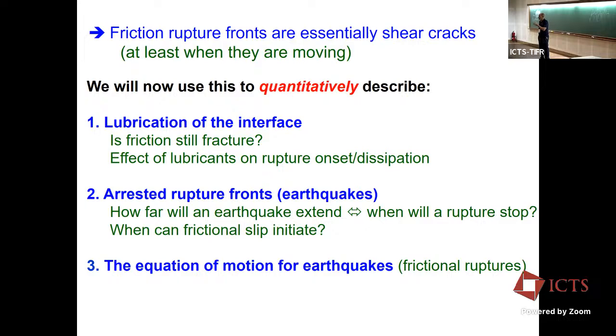First of all, I don't know, because we've never looked at a magnification where we could see individual contacts. We could, but then we couldn't see the rest of this stuff. But I think both are true. The contacts that exist as you push harder will grow, and then the free surfaces here will deflect and you'll get new contacts as well. Most of them will be plastic. Some of them might be just barely touching and they'll be elastic. But still, empirically, what we find is what Bowden and Tabor predicted, which is nice. It's nice to agree with somebody sometime. Any other questions?